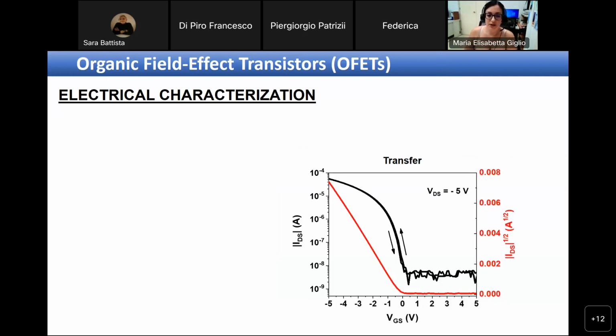Talking about the transfer, this is very important because we can calculate a lot of parameters that are of interest when talking about the performances. So the first one is the mobility. We calculate the mobility by taking the square root of the absolute value of the drain-source current, and then we make a linear fit of the current as defined like this, and by calculating the slope, we can extract the mobility, the field effect mobility.